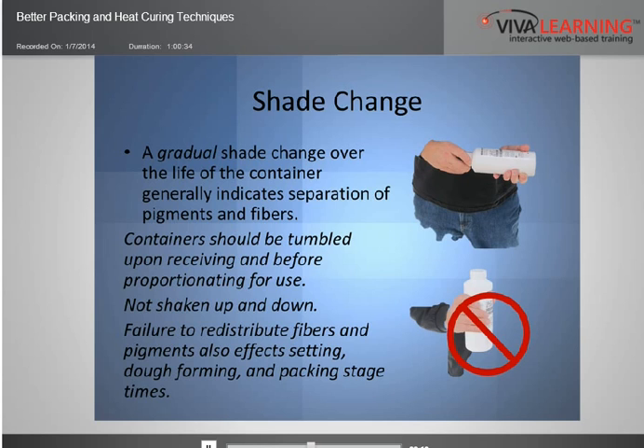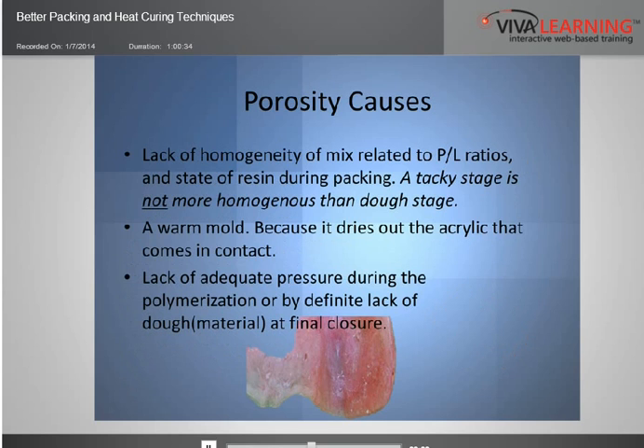Porosity causes. You know, guys are always calling about porosities. Put a bunch of dental technicians in a room together any place, and if they're doing dentures, at some point somebody mentions porosity. Again, I'm going to go back to the same things that I have to look at when I get a call, and that is a lack of homogeneity of the mix related to the powder and liquid ratios, and the state of the resin during pack. A tacky stage is not more homogeneous than a doughy stage. Dough is what you're looking for. You don't want to have any wetness, and you want it to be homogeneous. You want it to be doughy.